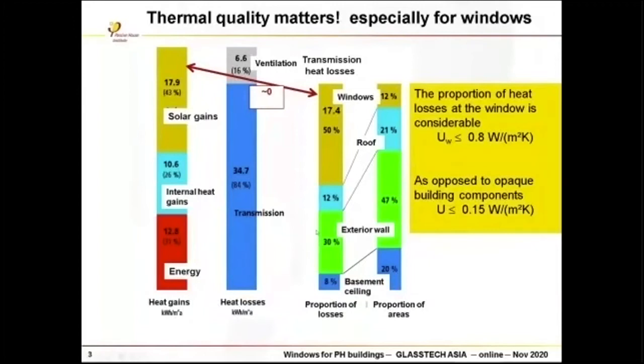Another part you see here, if you compare the fraction of losses and the fraction of area of windows in a building envelope. The yellow bars here show the losses and solar gains of windows and glasses. To keep this as low as possible, the U value of windows should be as low as possible as well. And this leads to a rough number of about 0.8 watt per square meter Kelvin.